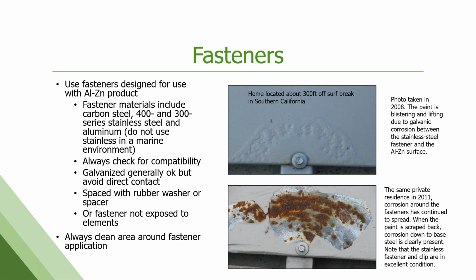And you can see that it's down. By 2011, when you peeled it all back, you were down to red rust. So we're down to base steel. There is no metallic coating left in those places. This would continue until that panel is completely disintegrated and gone. But you'll note that the stainless fasteners and the clips still look fantastic, and the stainless gutters still look fantastic. That's because of galvanic corrosion. So this complaint almost always comes in as a paint failure, and then we find out that's just a secondary issue. There's nothing for the paint to stick to anymore. That's why it's coming up.